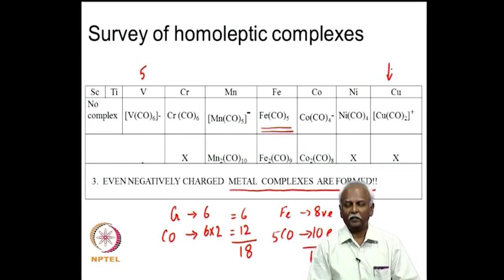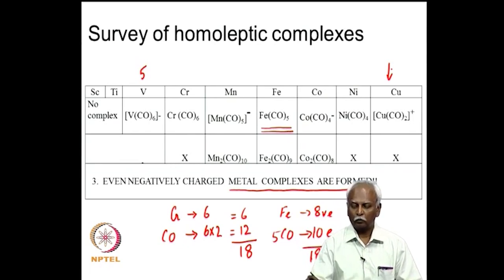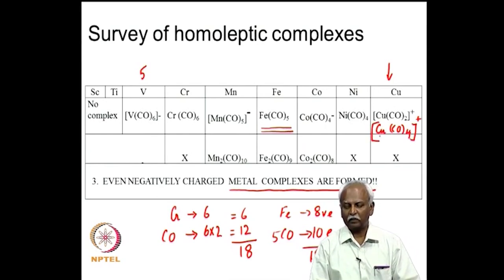It does not seem to follow the 18 valence electron rule, but you can generate a tetracoordinate CuCO4 complex also, and that is possible. People have generated a range of complexes in this case, but the number of complexes which are positively charged and have only carbon monoxide in the coordination sphere are rather small. Copper, gold, and silver are some of the species which form positively charged complexes. And you will notice that if it is CuCO4, then it would have a valence electron count of 18 also. So, let us proceed further.